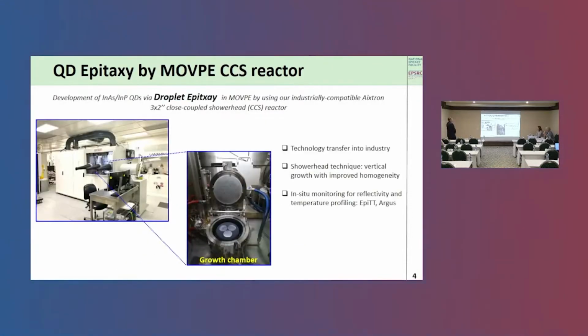So the quantum dots that we grow are grown in this MOVPE system. This is an Aixtron close-coupled showerhead reactor. This is actually a 3x2 system, and we say it's compatible with industry. It's very similar to the industrial designs that have much larger numbers of wafers, but anything that we do here can be translated mostly into industry. So this is the system that we're developing our quantum dots on to address that second technological issue.